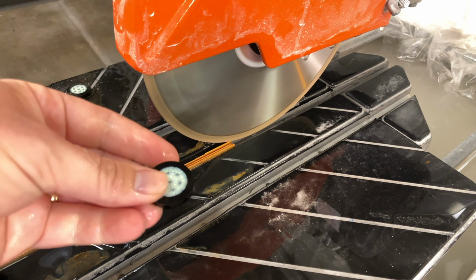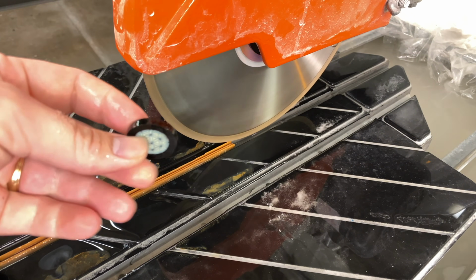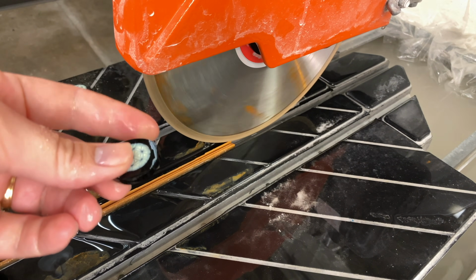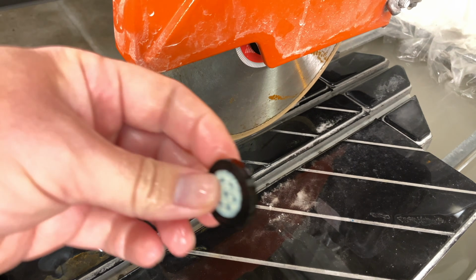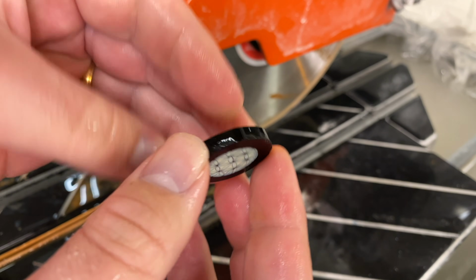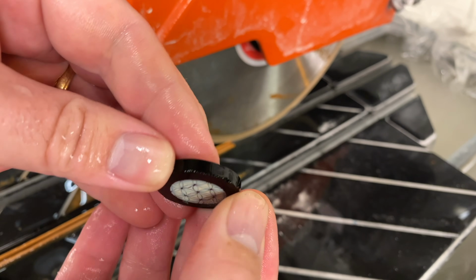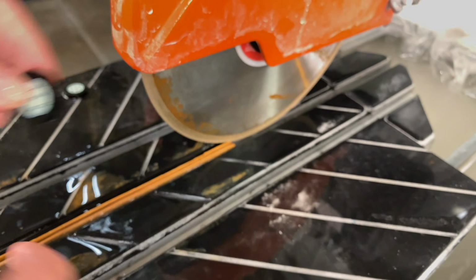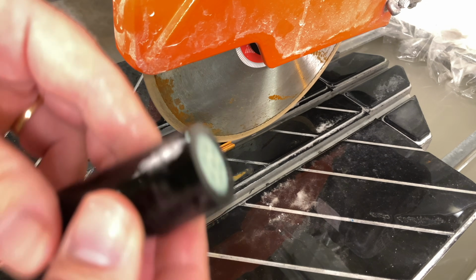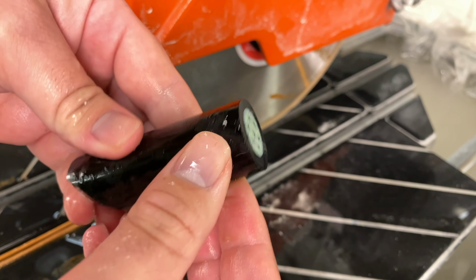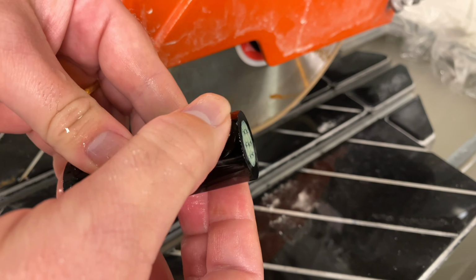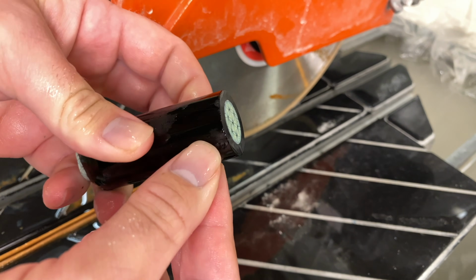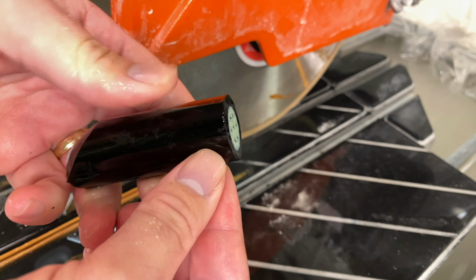And you probably noticed that it sounds very different when cutting with a sintered diamond blade versus the resin blade or the electroplated blade, and it went through the glass quite a bit faster. It also gives you a really nice clean cut. There's really no edge chipping on this. And you can look at this end as well. It really does a fantastic job and is significantly cheaper than a resin blade, just as fast, just as clean.